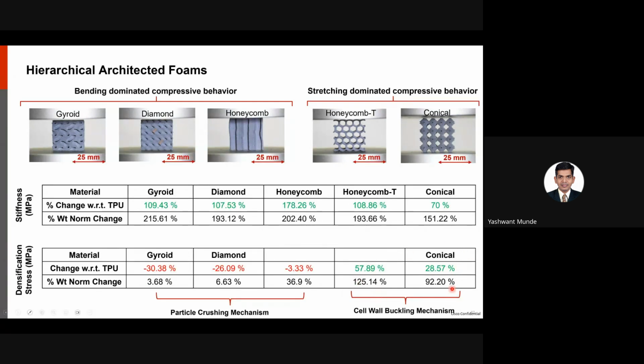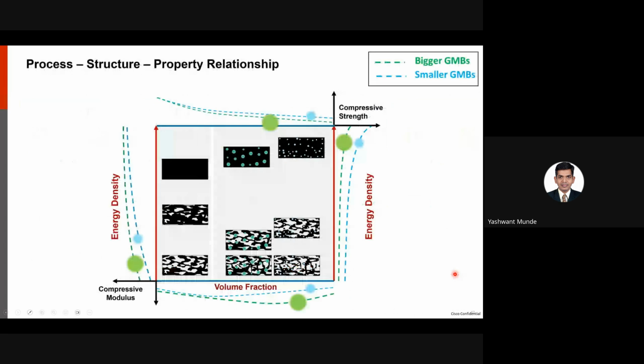Whereas here, because the peak or the densification is related to the buckling of the cell walls, it depends on the stiffness of the cell walls rather than the crushing of the particles. That's why we saw an improvement in the response here. So this was very informative, and it can aid future designs to be more stretching dominated to achieve higher stiffness.